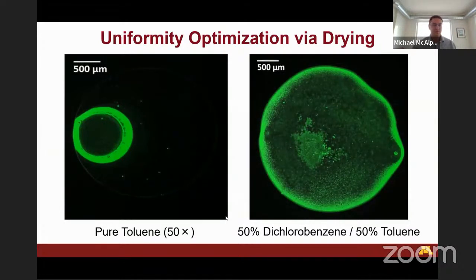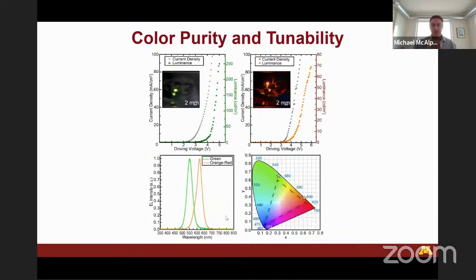So we don't do fundamental research really, but we can use tricks from the fundamental world to explore these applications. So this allowed us to fully 3D print two cadmium selenide devices. One is a green, one is an orange. They're different size particles, both cadmium selenide. And of course, being quantum dots, they have good color purity and good saturation. The entire structure is 3D printed: the electrodes, the quantum dots, the top liquid metal contact.